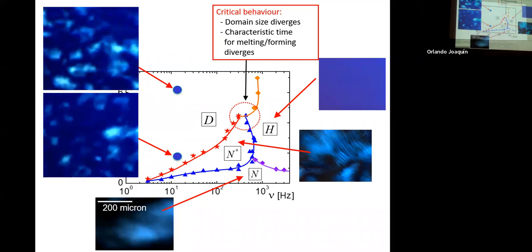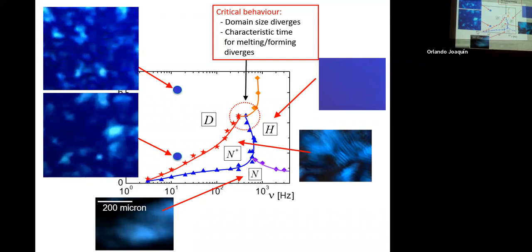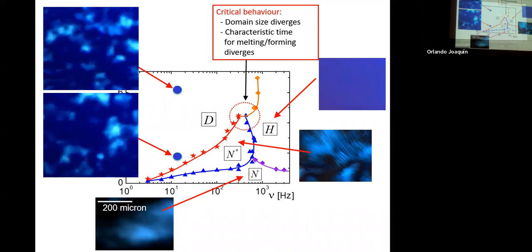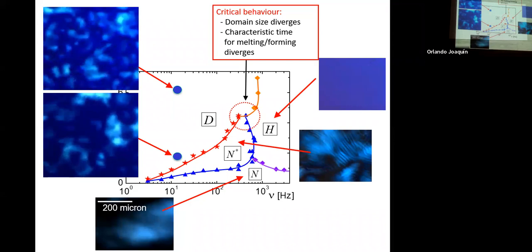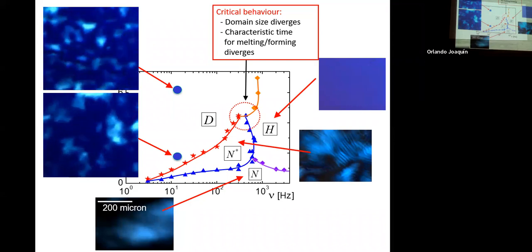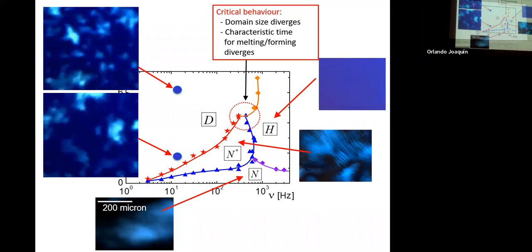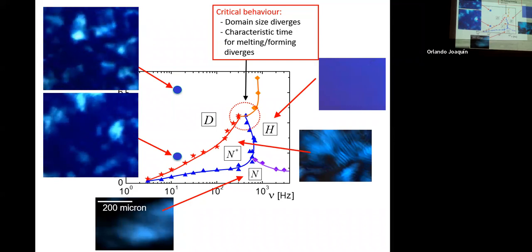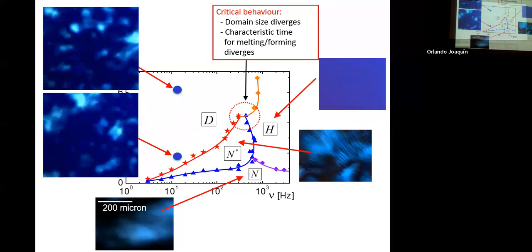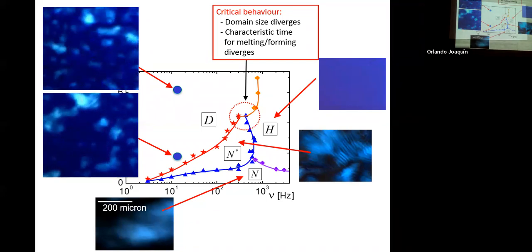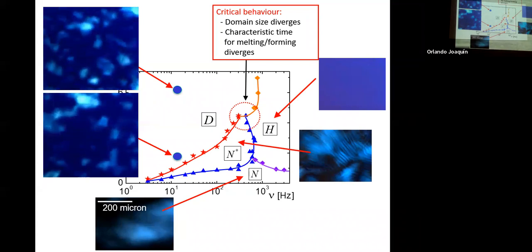In particular, at this point, you will have critical behavior in the sense that the average domain size you find diverges as you approach this point. And also the time scale on which this melting and forming occurs also diverges. So in that sense, you could interpret this as a type of non-equilibrium critical point. And you can actually measure the critical exponent, which we did, but I'm not going to talk about it.